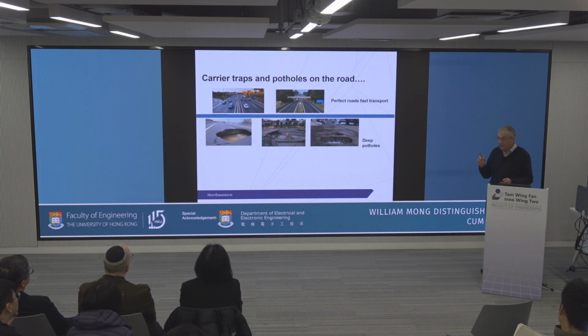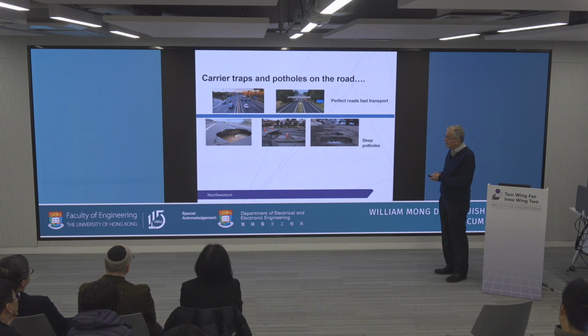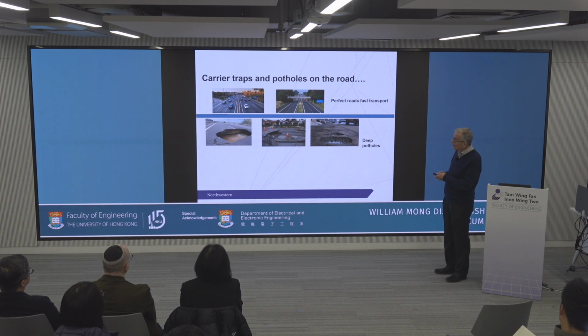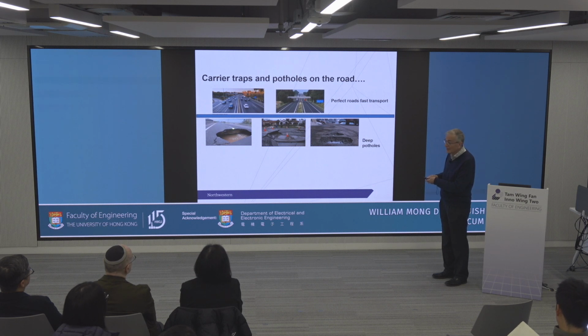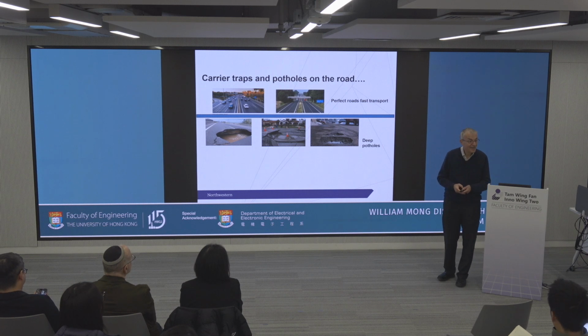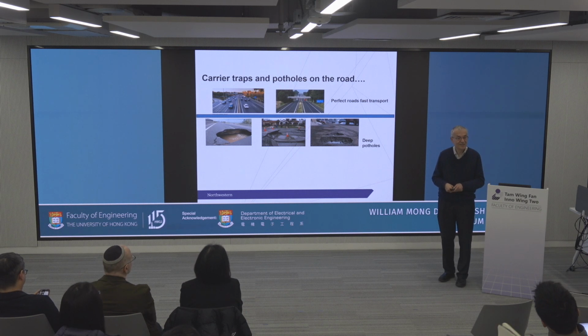If, however, this highway develops holes, big holes like that, and one of these carriers falls into one of these, you're stuck. You're not going anywhere. Now, the next hole could be over here. So between the holes, it could be perfect, but the existence of a hole is going to prevent you from going there. That means that your device is dead.